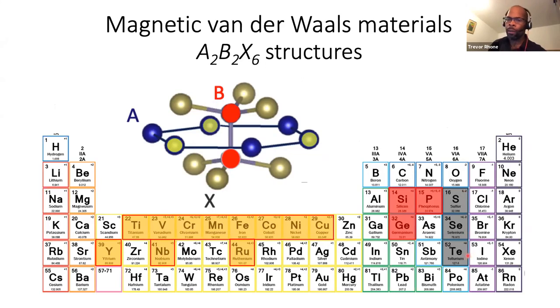Okay. So we can then do the calculations and collect the data and compare this quantity I'm calling delta E, which is the difference between the DFT energy for the ferromagnetic configuration and that of the anti-ferromagnetic configuration. And so if this value is negative, that means the ferromagnetic structure is lowering in energy, and therefore the DFT theory predicts that this material should be ferromagnetically ordered. If the reverse is true, if the AFM has lower energy, then it predicts that the structure should have the AFM order in nature.